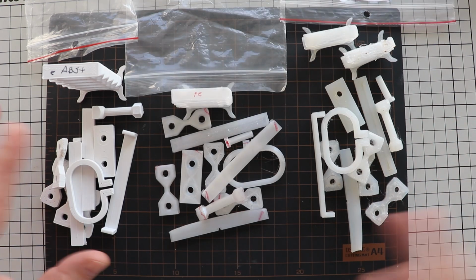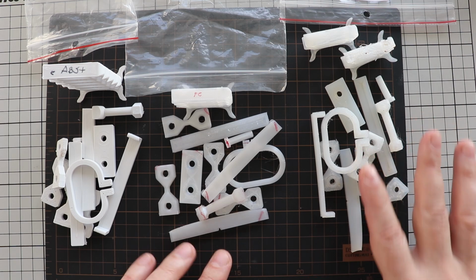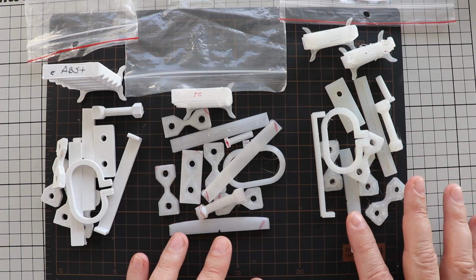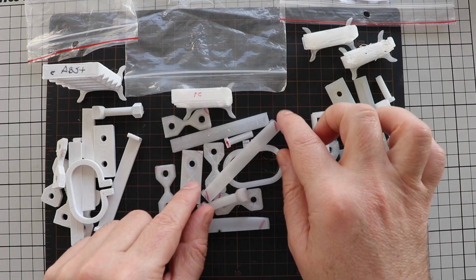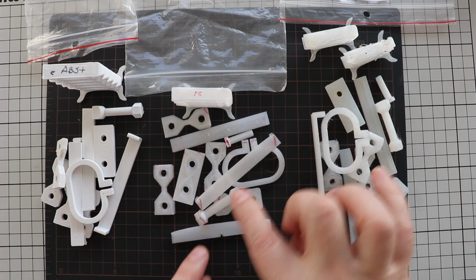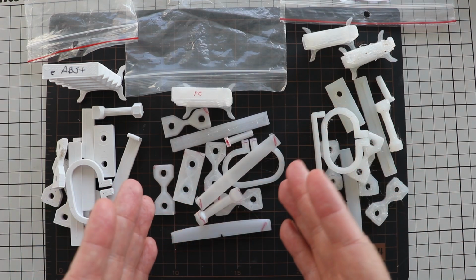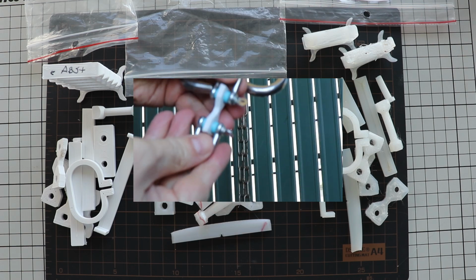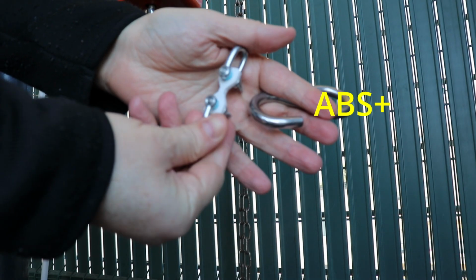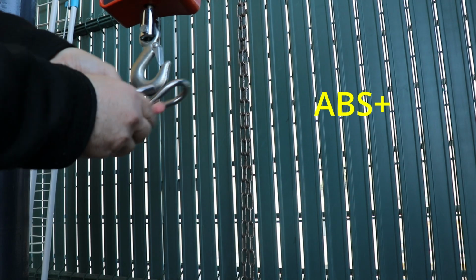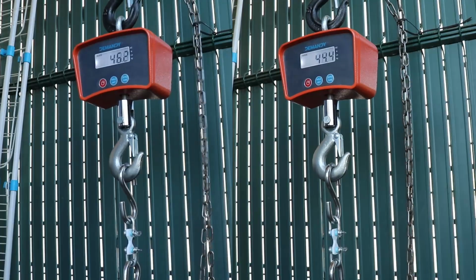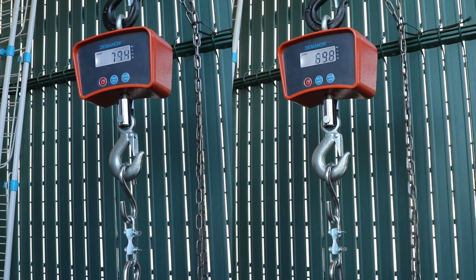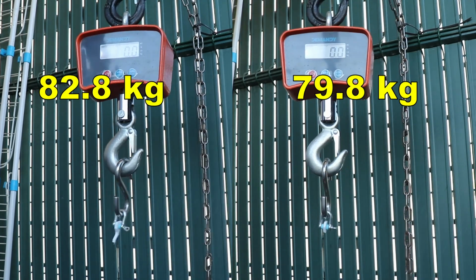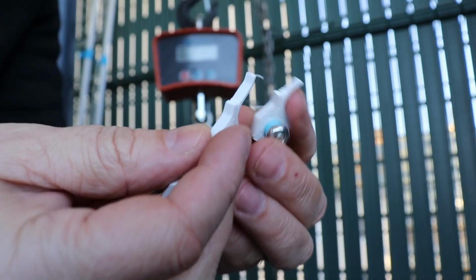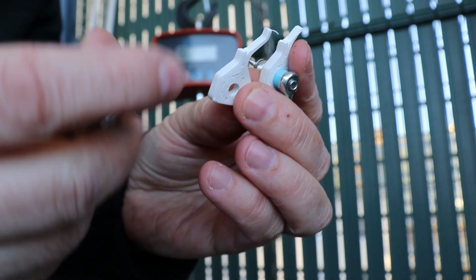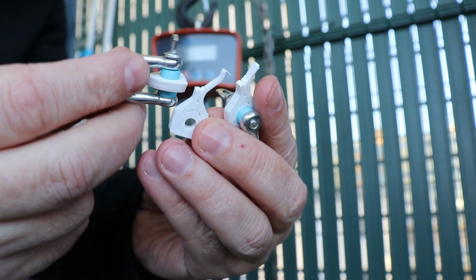As you can see, ABS is in white color, but PC and nylon are very similar, in some kind of transparent color. So I marked the PC test specimens with this red line, just in case it's easier to follow on the cameras. And I'm starting with the tensile test. These test specimens are printed in horizontal position. The smallest cross-section area is 4 by 4 millimeters. And they broke on very similar load. And this reminds me of the weaker layer adhesion.